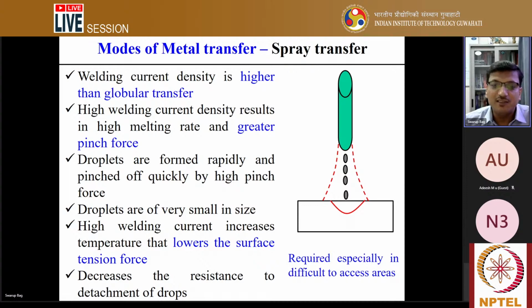And when using a high welding current, the overall temperature increases, because at high welding current the heat generation at the electrode will be much more. But at the same time, when the temperature is very high, it lowers the surface tension force. The surface tension force is the drop holding force, which tries to keep holding the droplet. So once you lower the drop holding force, the other forces dominate, and very quickly the droplet can be created. So that's why at high welding current, spray-type metal transfer is possible.